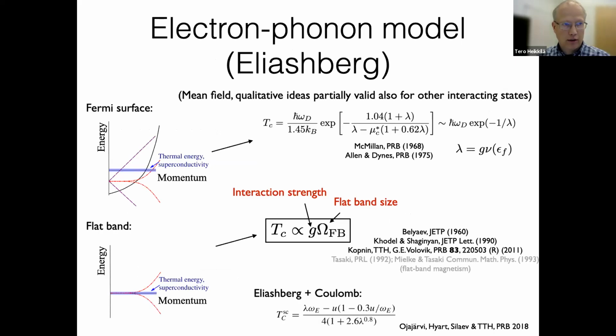Okay, so once you do this Eliashberg theory, what you get in the Fermi surface case is this Allen-Dynes formula, McMillan formula, I guess it's called, where the TC is basically exponentially suppressed, but there are some corrections from the so-called pseudopotential terms, and there are also higher order terms in lambda. These are based on so-called Migdal's theorem, which states that for Debye frequency small compared to the Fermi energy, you can go to higher order effects in lambda, but still do self-consistent Born approximation in the electron-phonon coupling. This actually fails for flat bands. I will discuss it in a moment.